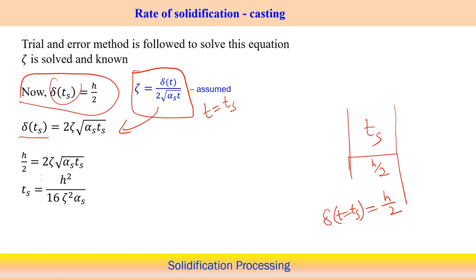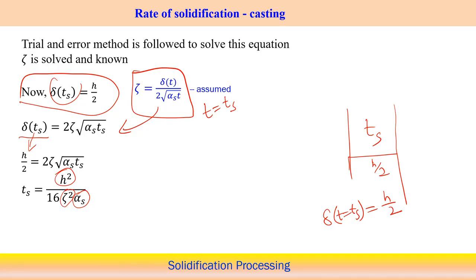Now delta ts equals h by 2, so we put delta ts equal to h by 2, equal to twice zeta root of alpha s and ts. Now ts can be calculated in terms of other terms. h is defined, alpha is the material property that we can easily calculate, and zeta we need to calculate, and then we can estimate the value of the solidification time in this particular case. In any step, we need to calculate the value of zeta first in this expression.